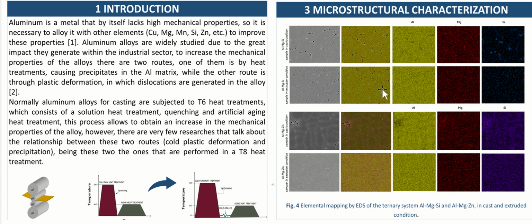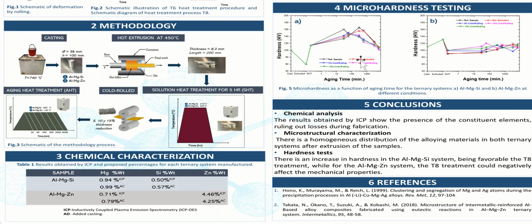According to the results obtained by EDS mapping in Figure 4, it can be seen that both ternary systems, aluminum-magnesium-silicon and aluminum-magnesium-zinc, in extruded condition, present a higher homogeneity of the alloying elements compared to the samples in cast condition, where the highest concentration of elements such as silicon and zinc are found around the pores and cracks. In the Vickers micro-hardness tests, for the samples containing silicon, Figure 5a, it can be seen that there is an increase in hardness after the samples are submitted to the thermal treatment of solubilization and after the deformation process by rolling. However, the maximum hardness value obtained is in the reference sample, without deformation process.